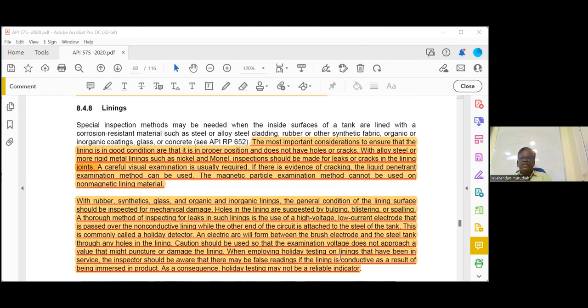When employing holiday testing on linings that have been in service, the inspector should be aware that there may be false readings if the lining is conductive as a result of being immersed in the product. As a consequence, holiday testing may not be a reliable indicator. See, remember yesterday in 652, in service, if you are going for lining, first you have to dry the lining, because if there is moisture absorption, water absorbed inside, it becomes conductive. Okay.